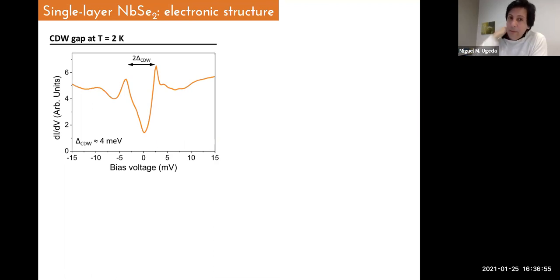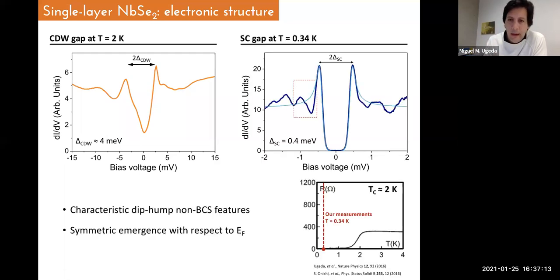There are other reports that claim that the critical temperature in the monolayer range goes up to 150 Kelvin, but this couldn't be in good agreement with the size of the charge density wave gap that we observe. So if we cool down the temperature below 2 Kelvin, according to our previous transport experiments, the superconductivity state should be fully developed at the base temperature at which we work. And actually what we see is something that reminds of a superconducting system. The light blue curve that you see here is the BCS fitting of this curve. And actually it fits very well, including the coherence peaks.